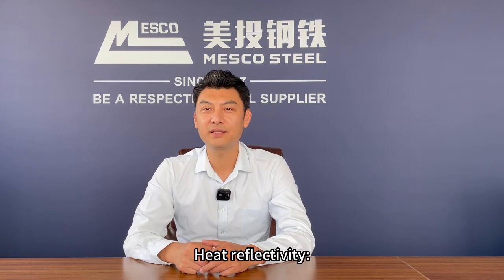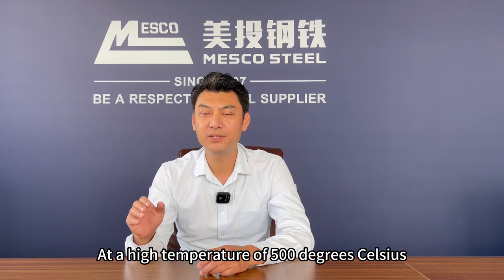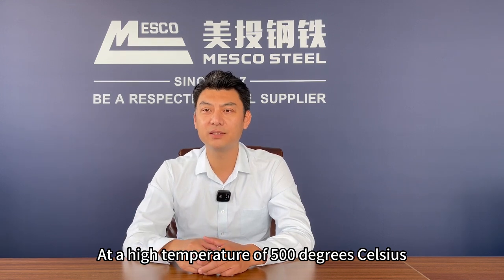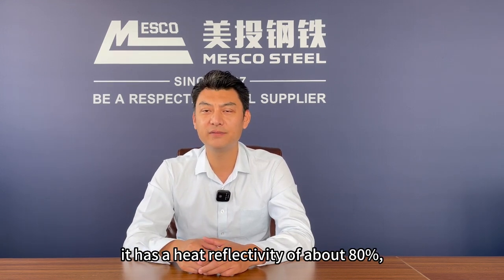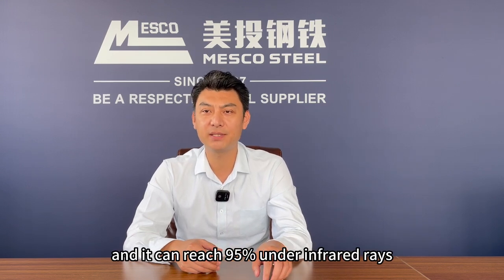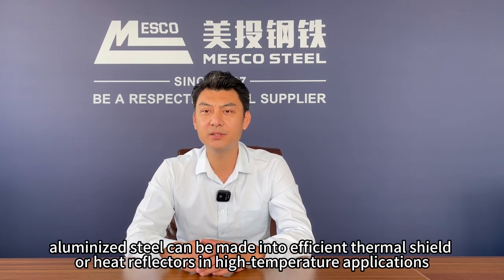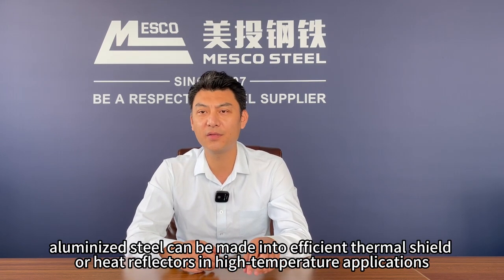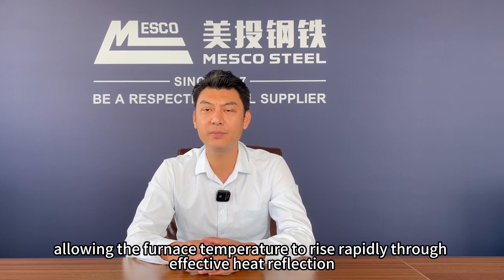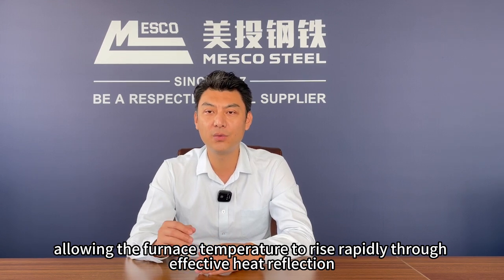2. Heat reflectivity. At a high temperature of 500 degrees Celsius, it has a heat reflectivity of about 80%, and it can reach 95% under infrared rays. Therefore, aluminized steel can be made into efficient thermal shields or heat reflectors in high temperature applications, allowing the furnace temperature to rise rapidly through effective heat reflection.